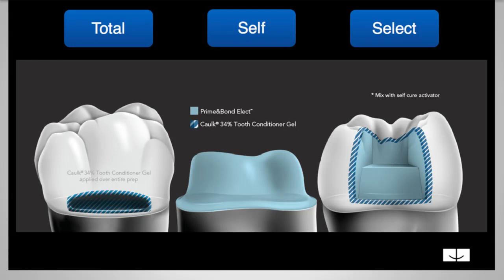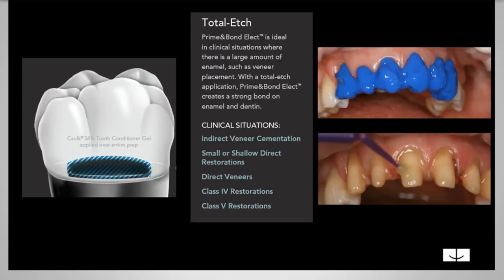Now remember, self-etch bonding agents did do rather well on dentin alone, but when it's the enamel, that's where the problem lies. So if you just have dentin, then self-etch is okay. So if you're bonding the crown in and it's mostly just dentin, then using a self-etch technique is sufficient. So again, total etch in these situations, if you're doing veneers, or if you're doing class 5 or something that's shallow, doing a total etch is what I would recommend.